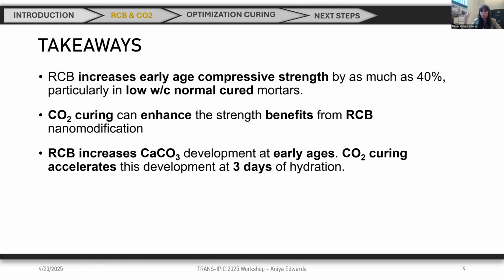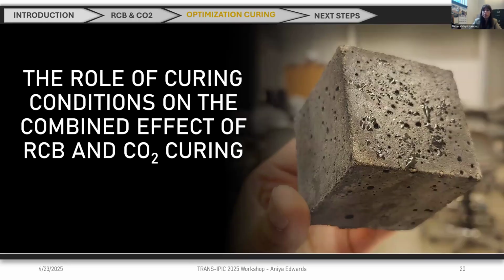When we go further, as happened with other nanomaterials, if you put too much, then you will have a detrimental effect. So we have to be careful with that. And recovered carbon black increases the calcium carbonate at early ages on the surface.